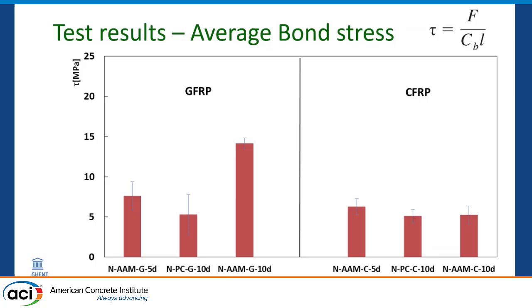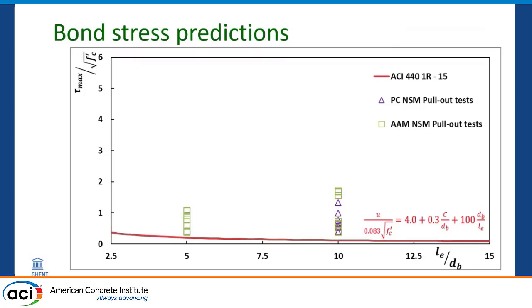When it comes to carbon fiber, there is actually not a lot of fluctuation. So the Portland cement 10D and the alkali-activated 10D are similar, and alkali-activated with 5D develops slightly higher stress. And here we can see the curve from ACI 440.1R, with a different C for the different bar position, and we see that all the results are over the curve.